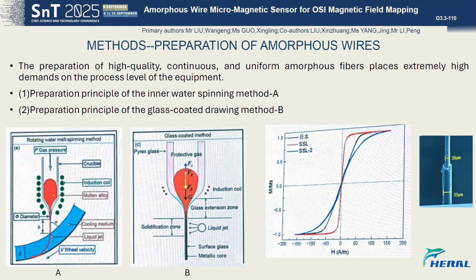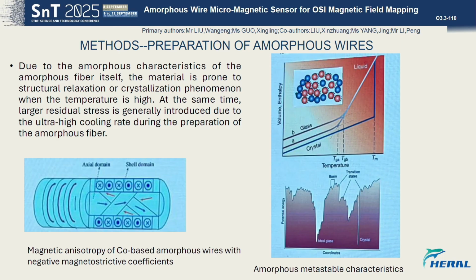The preparation of high-quality, continuous, and uniform amorphous fibers places extremely high demands on the process level of the equipment. For example, the preparation principle of the inner water spinning method and the preparation principle of the glass coated drawing method. Due to the amorphous characteristics of the amorphous fiber itself, the material is prone to structural relaxation or crystallization phenomenon when the temperature is high.